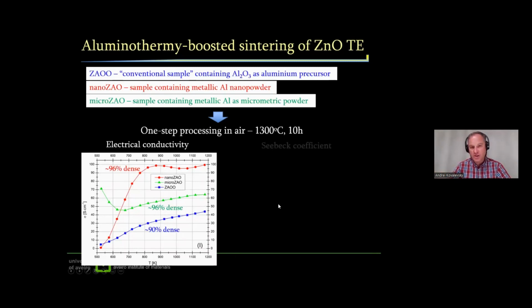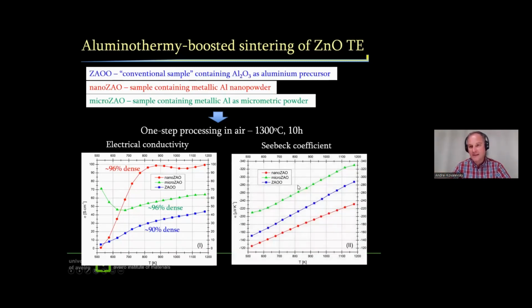Also some changes in Seebeck coefficients, which evidence quite significant variation of the charge carrier concentration, meaning we have changes in the doping mechanism. We can introduce more doping at a time, which in many cases is advantageous.